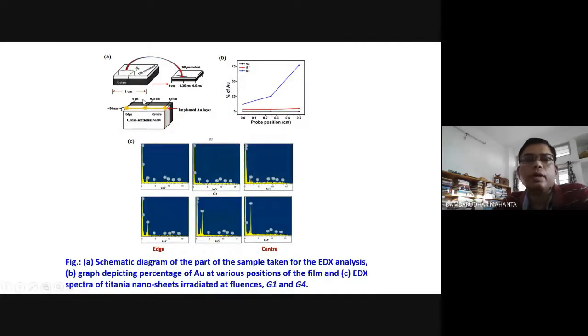In this case, this is a schematic. Top 1A is showing a schematic, a cartoon. We have sliced this part. This was an aluminum sheet on which titanium nanosheets were there, and this section was cut and transferred. Then it was flipped, and since gold was implanted, the implantation of atoms, as all of us know, follows a Gaussian trend. Since this sample was very small, we cannot measure every millimeter or so, but we have taken 3-4 sites and tried to measure the percentage of gold in those regions using EDX, here, here, here. And we found that it is following this trend. So with higher dose, there is a growth.